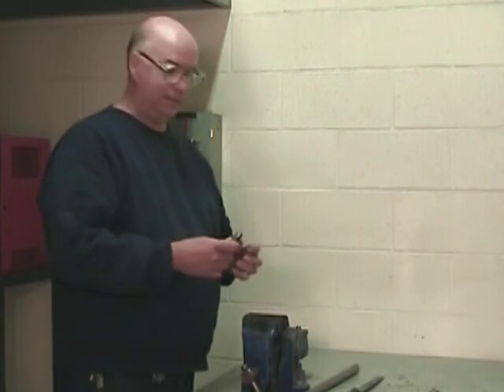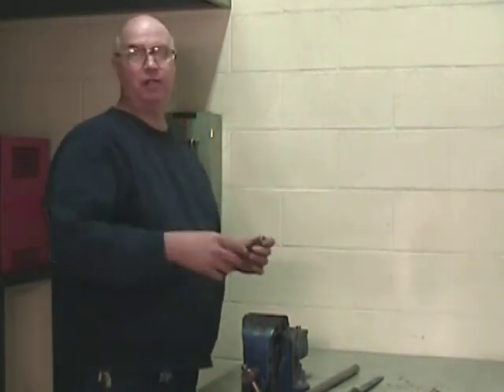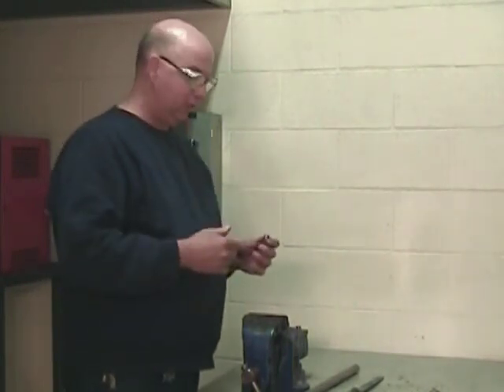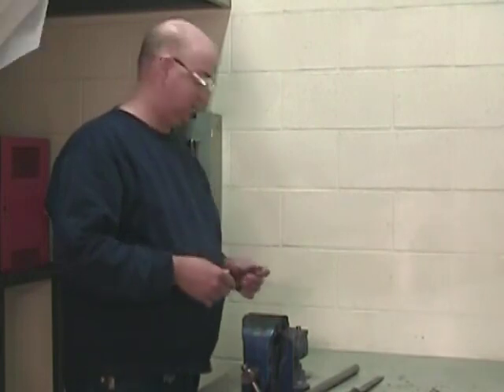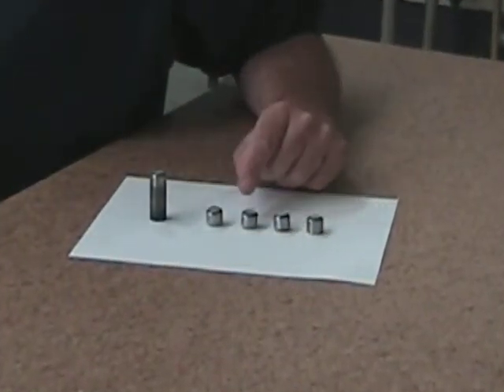Okay, so we've broken all the segments. We're going to bring all this over to the surface plate so we can look at the results. Well, we've completed the testing, and it'd be a good time to take a look at what we can learn from this test. The first thing we learned was that pieces 1, 2, and 3 were virtually the same hardness.